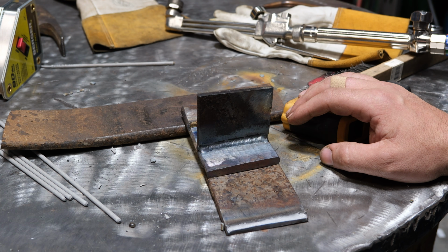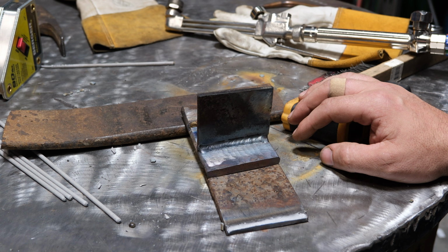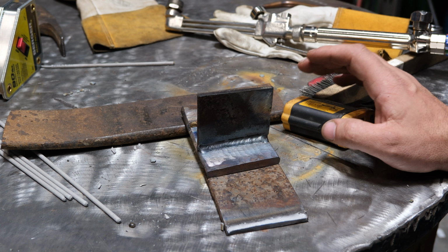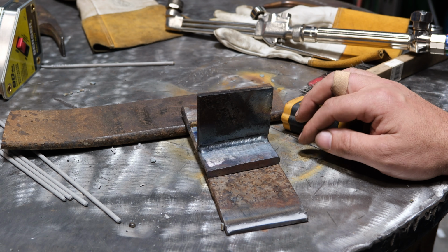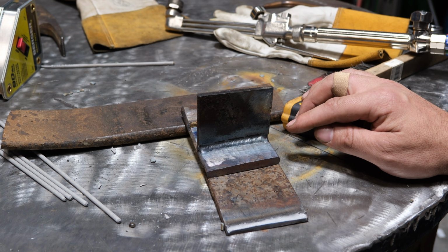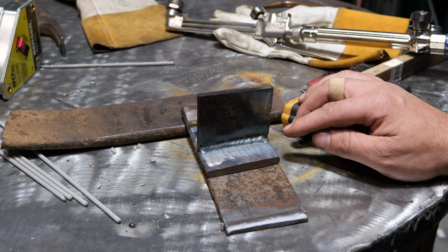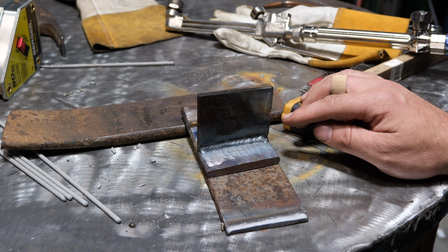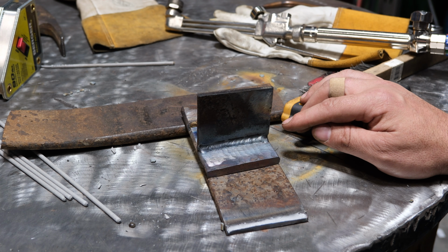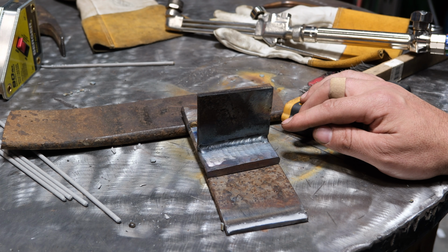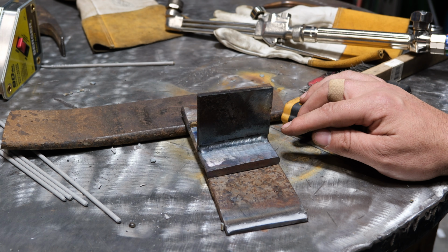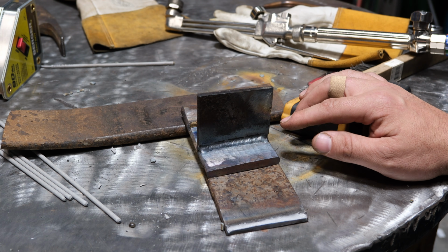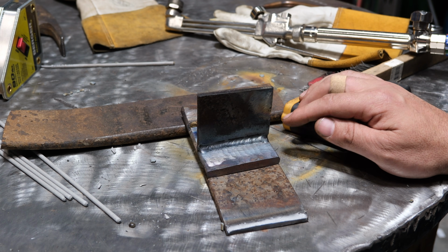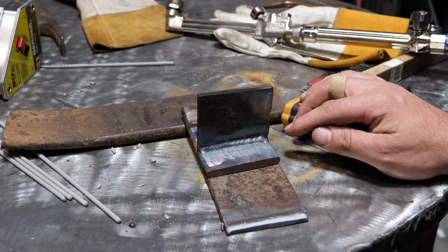It's in your best interest to keep rods properly stored in your garage or in your trail rig or whatever if you're going to be doing a repair like this, because if the rod absorbs moisture, in the case of 7018, that moisture will get into the weld pool and will create what's called hydrogen embrittlement. This material is highly susceptible to hydrogen embrittlement, and that will cause failures as well because it's going to lose its ductility. As far as ER70 with TIG and MIG, generally speaking, you're going to be just fine with that.